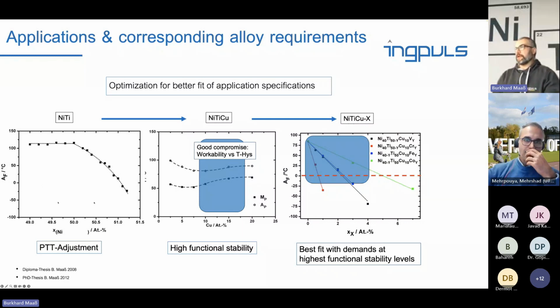And you see here, as you come over the threshold of, let's say, 7.5 atom percent copper, then you come from a B2 to B19 prime transformation to a B2 to B19 transformation. So this is where the hysteresis gets really small, but this is also where the material becomes really brittle. We have found a way to work this material. We can produce very nice materials which are B2 to B19 prime, and they have a small hysteresis. But what you also see is that the phase transformation temperatures are far from being pseudoelastic at room temperature.